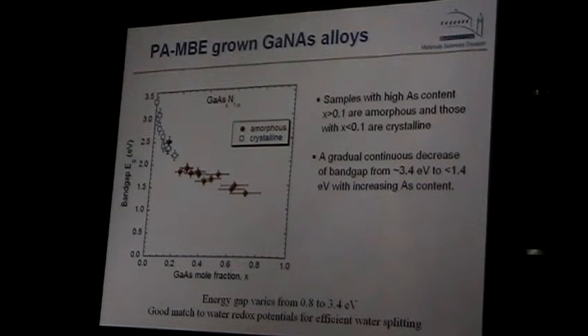And basically, I said, we were talking about how they don't want to mix. So what's happening is you have to lower the temperature, and when you lower the temperature you also force a lot of nitrogen or gallium or arsenic to change the growth condition. So what they did, they grew gallium nitride arsenide over the whole composition range. And that was quite an achievement. It was the most recent achievement.